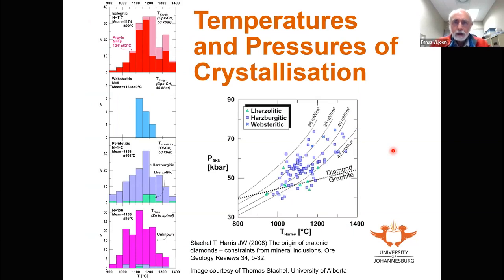Now, it is possible to determine the pressures and temperatures at which diamonds crystallize by using coexisting minerals. If you have coexisting minerals occurring as inclusions in diamonds, as they are sitting in the mantle and as they are being captured by the diamond growth event, the inclusions in the diamonds will record particularly the temperature, but also the pressure at which those diamonds were crystallizing.